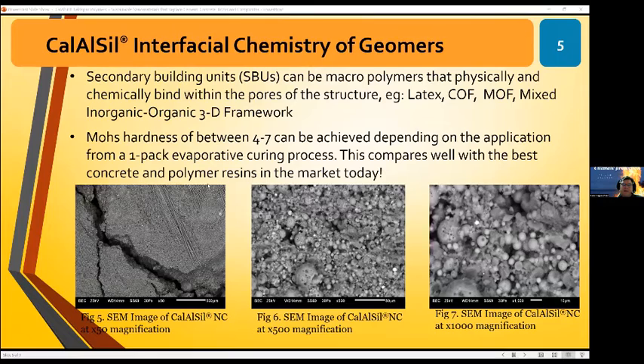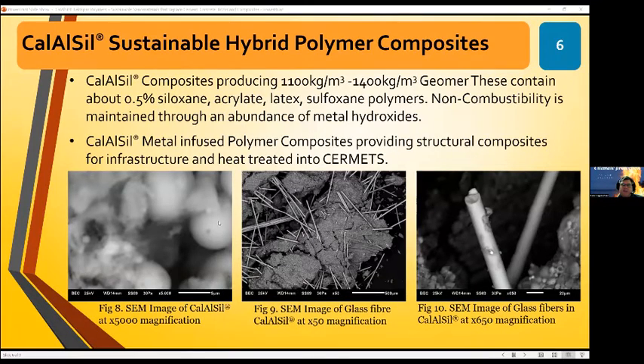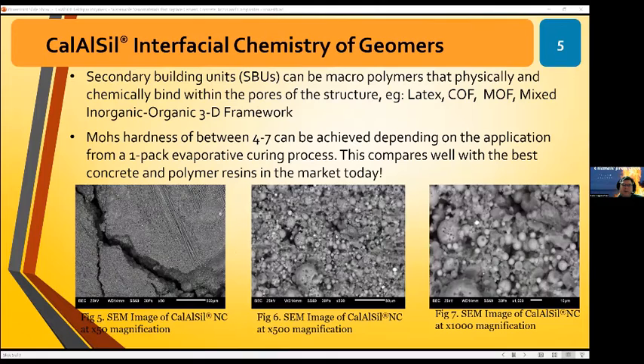Just skipped over one there. So the interfacial, this is some of the newer work that I had done over summer. Secondary building units can be macropolymers, like I've explained, covalent organic frameworks, metal organic frameworks, latex, and mixed inorganic, so zeolite organic frameworks effectively. Now, believe it or not, just simply by painting the resin out, and this is compared to, say, a cement paste.